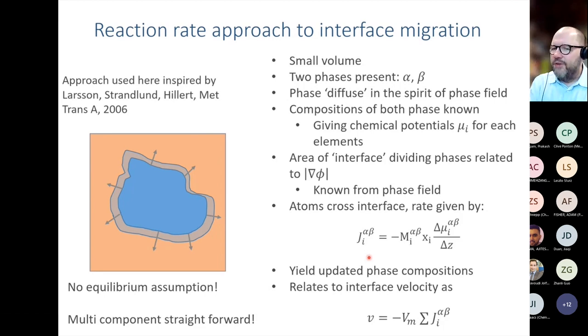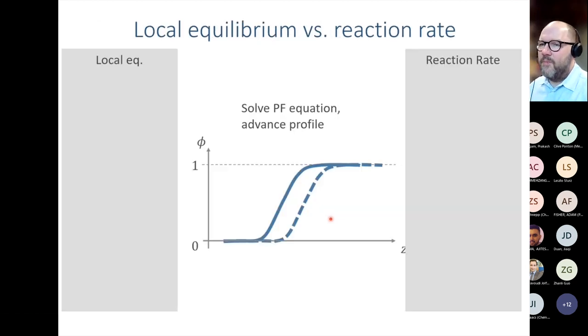We also find that extending this to multi-component is very, very straightforward, because all we need to do is just have that equation that describes the flux. We need one of these for each element. So if we had a unary system, we would have one of them. If we had a binary, we had two. If we had a 20-component system, we would have 20 of these equations. The computation effort would increase, of course, but the extension from unary to a multi-component system is extremely straightforward.